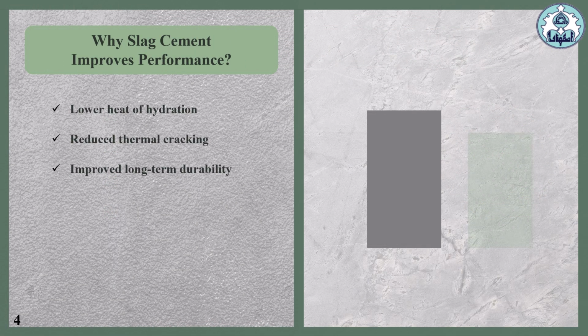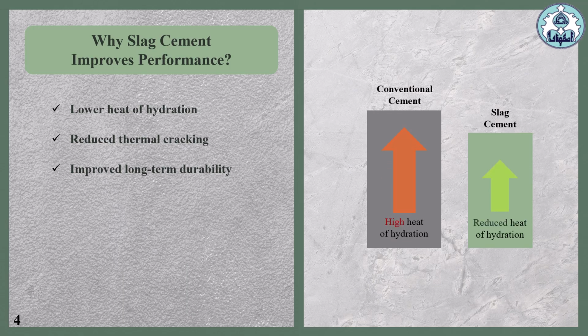Slag cement improves concrete performance due to several key properties. First, it generates a lower heat of hydration compared to Type 2 cement, which significantly reduces the risk of thermal cracking during curing. Second, this lower heat helps maintain uniform temperature throughout the structure, ensuring better structural integrity. Finally, slag cement enhances long-term durability by increasing resistance to chemical attack and improving overall sustainability, making the concrete more resilient over time.